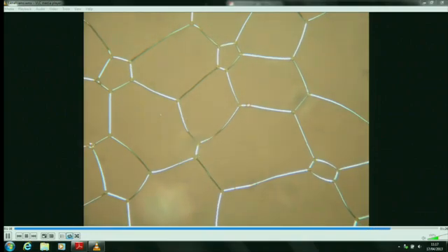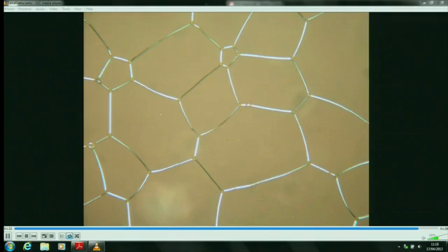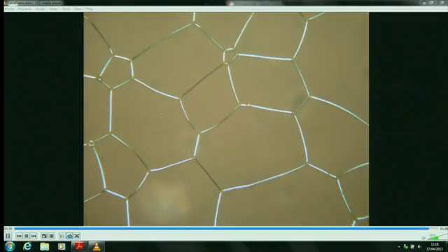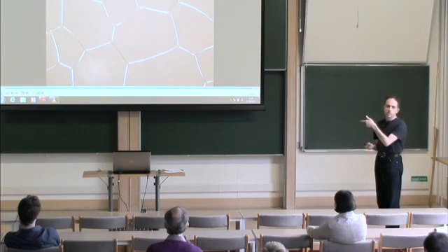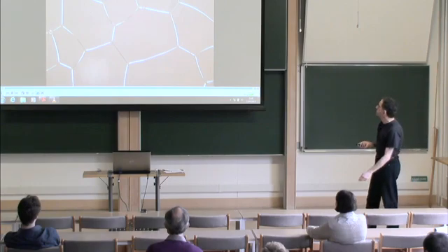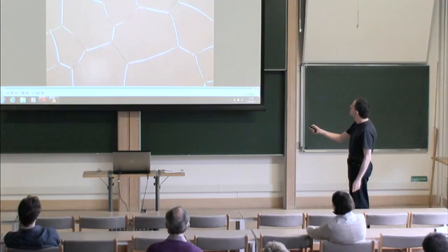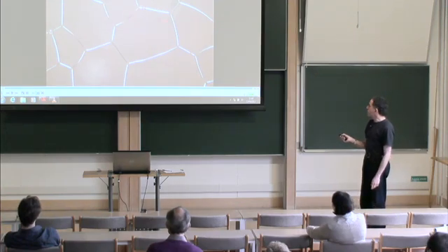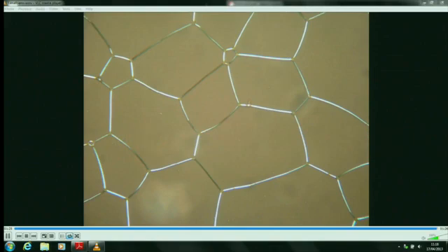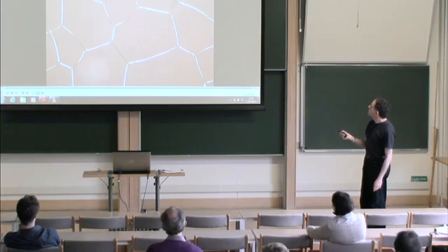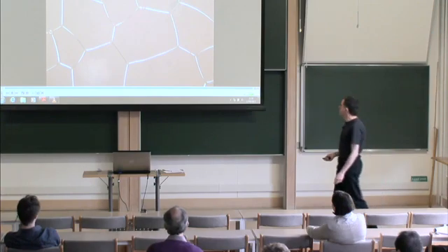This is what's called the T2 topological transformation, where a bubble disappears. You also see T1 topological transformations, which is when bubbles switch neighbors. First you have two bubbles that are not neighbors, and then the edge separating the two that are neighbors shrinks, so that two that were not neighbors become neighbors, and two that were previously neighbors become non-neighbors. I think that one's going to go as well. No, I think it's stopped now. We've reached the latest time that this went, but that bubble, which is five-sided, had we waited a little longer, as well as that one, would also have disappeared.